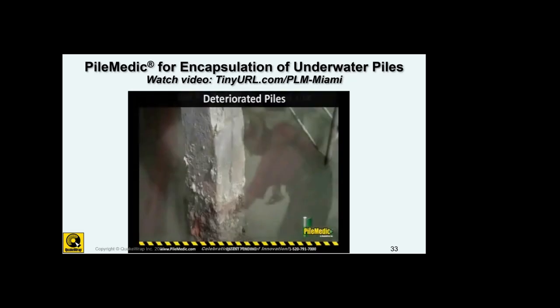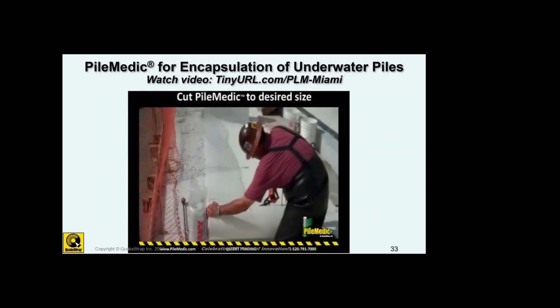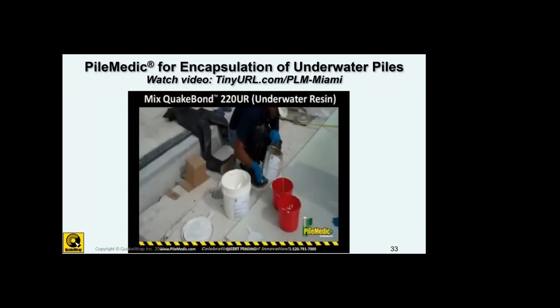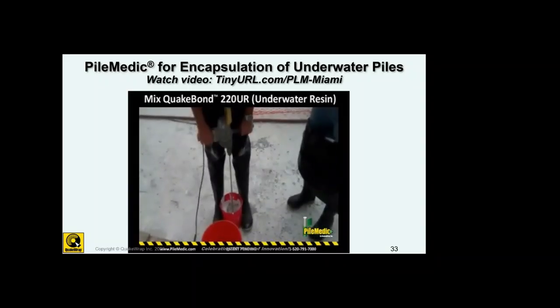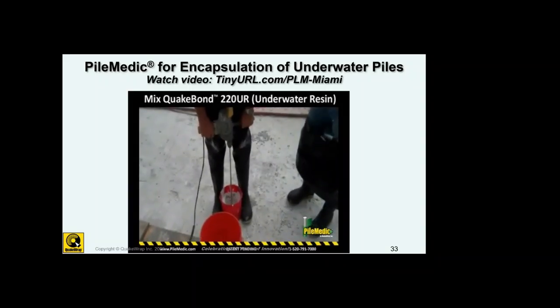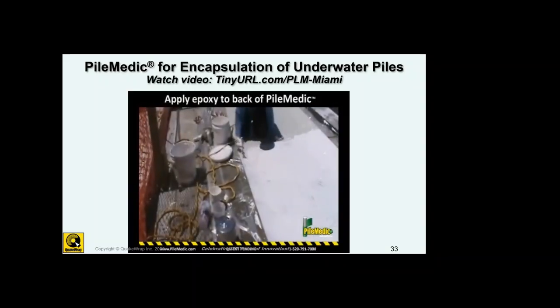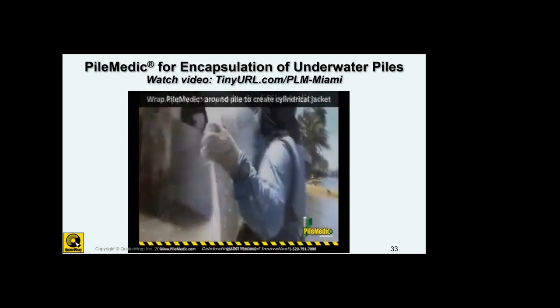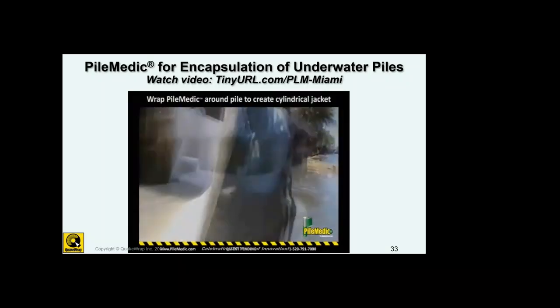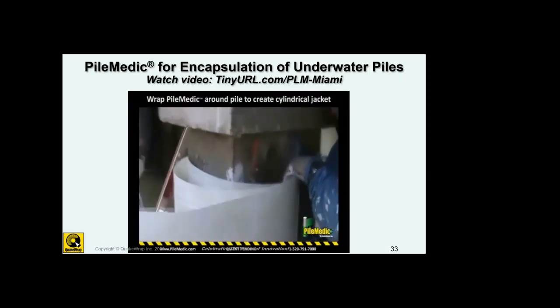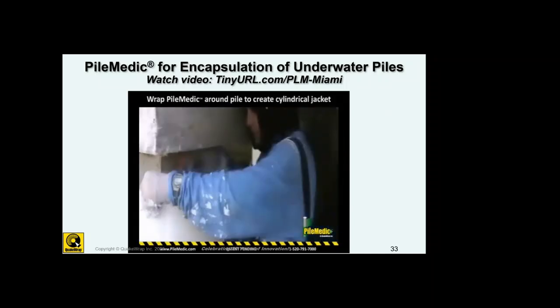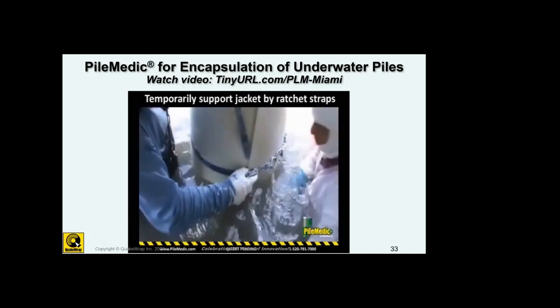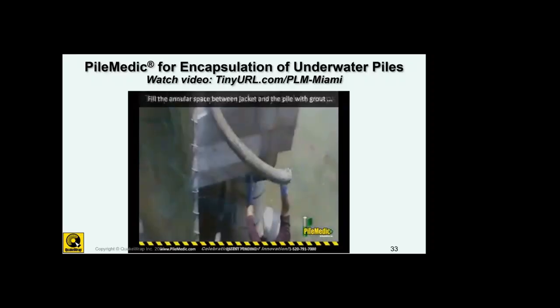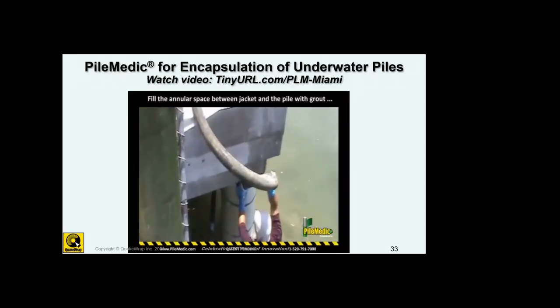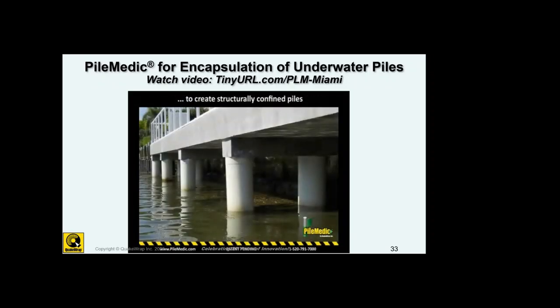We didn't have all the bells and whistles and the spacers there, but you see the contractor can cut the laminate from the roll. This epoxy that we provide cures underwater, so you do not need any cofferdams on any of our projects. Here it was shallow water, so they walk in there, wrap the laminate around the column or pile, hold it together with ratchet straps, and then fill the annular space with grout. And here is the finished project.